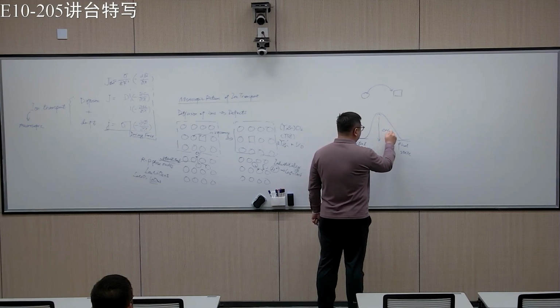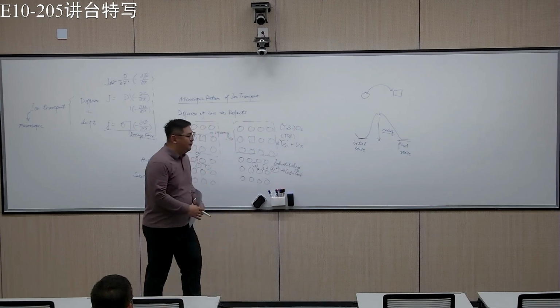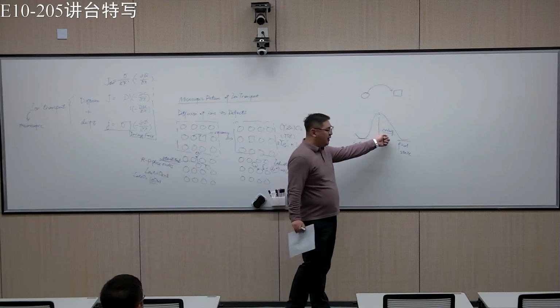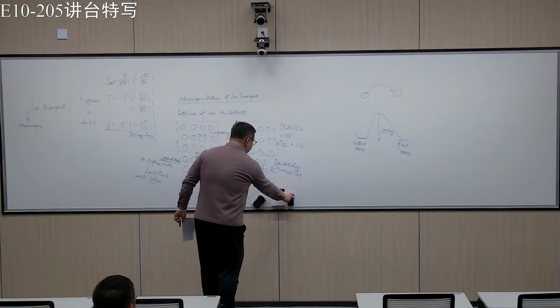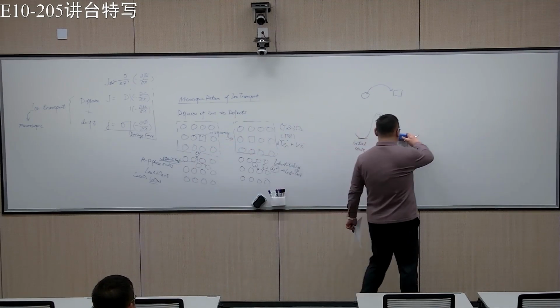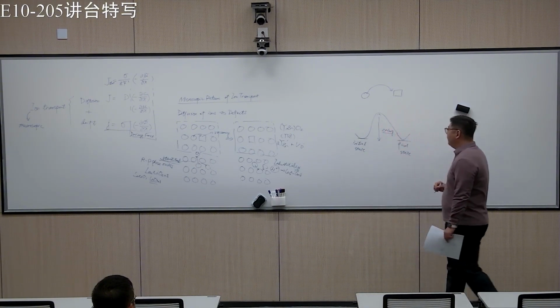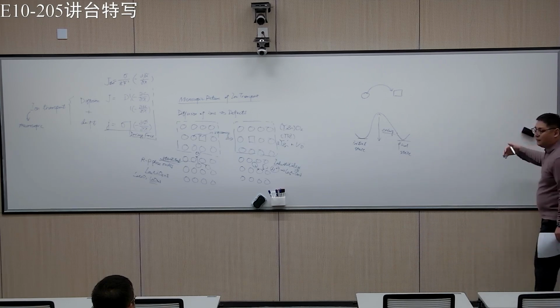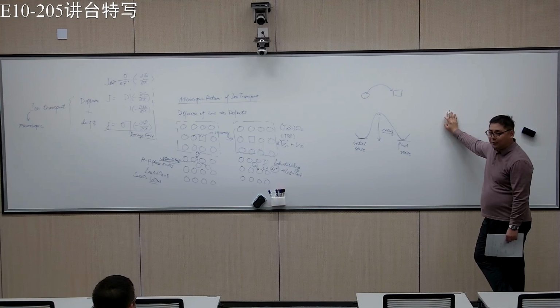Usually it's the so-called migration enthalpy. Okay. So it really should be the migration Gibbs free energy, but we neglected the entropic contribution. Okay. So since it has to overcome the barrier, of course it's somewhat activated.